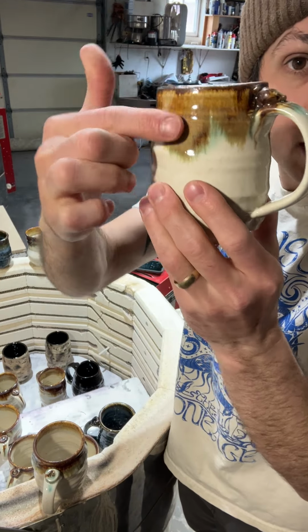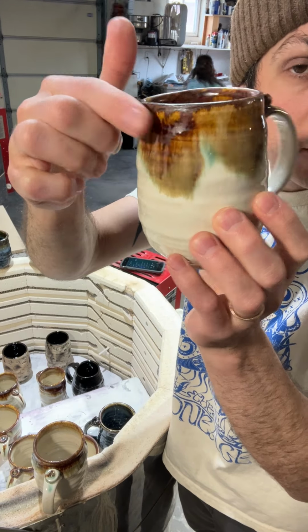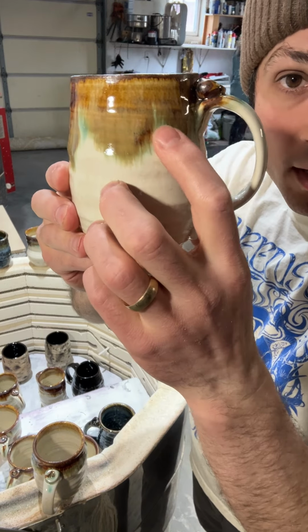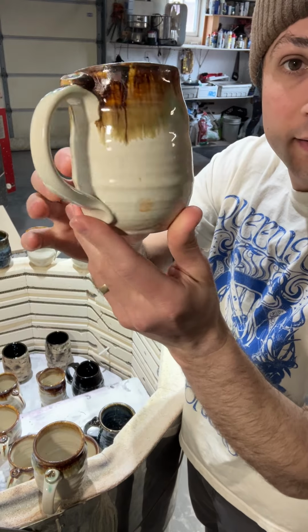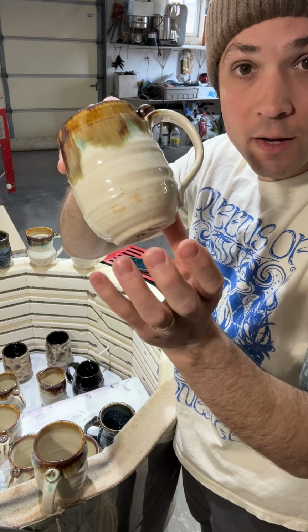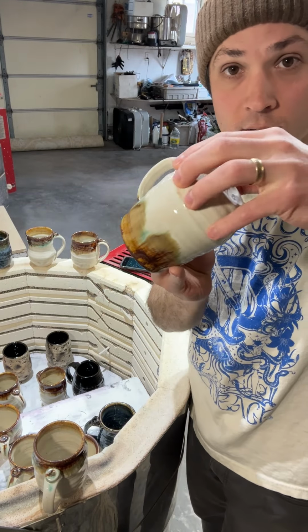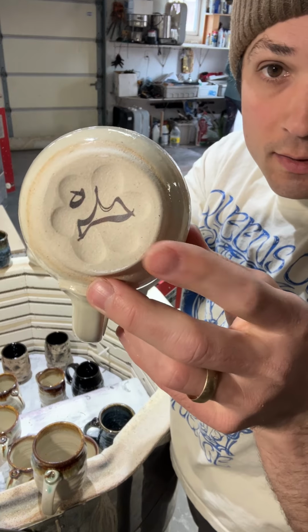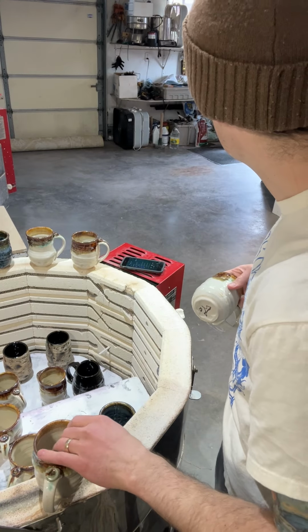This one I brushed up and down in a thinner coat, got a little thicker, and then brushed copper underneath. Then these marks are from my fingers, from dipping the pot down in the ash glaze, and then the signature is iron oxide.